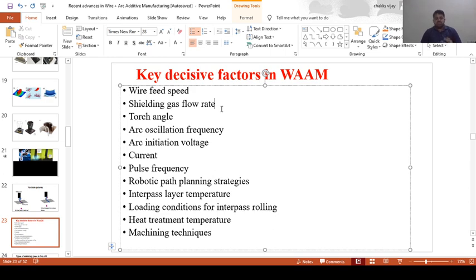Then torch angle. Why torch angle? That matters a lot. This torch angle will be the key decisive factor for attaining specific texture. For example, if you are taking a material which is a face centered cubic metal, say stainless steel 316L, and we are concerned to produce a component in a preferential texture, so in one particular texture all the grains should be oriented, then of course we have to give importance to torch angle. For each and every torch angle, the texture will keep on getting altered.